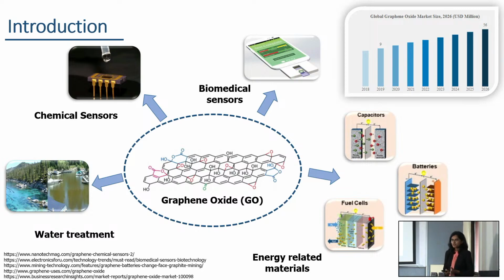Due to the presence of these polar oxygen functionalities, graphene oxide can be easily dispersed in water and other polar solvents. At the same time, graphene oxide has a high surface to volume ratio and can be chemically modified or functionalized, serving these oxygen functionalities as active sites. Because of these properties, graphene oxide is widely used for different applications such as development of sensors, energy related materials, as well as for water treatment and many more.